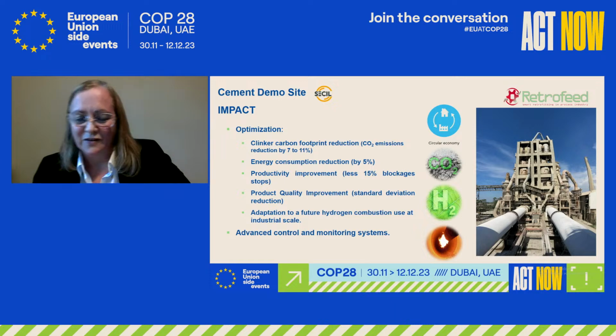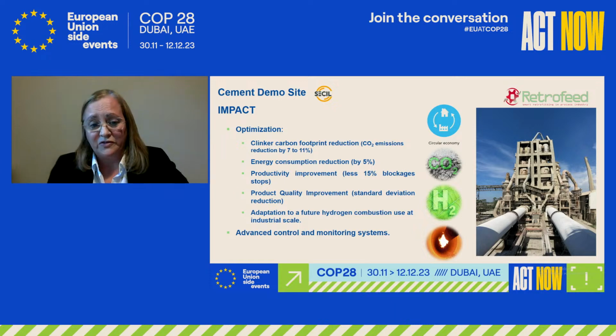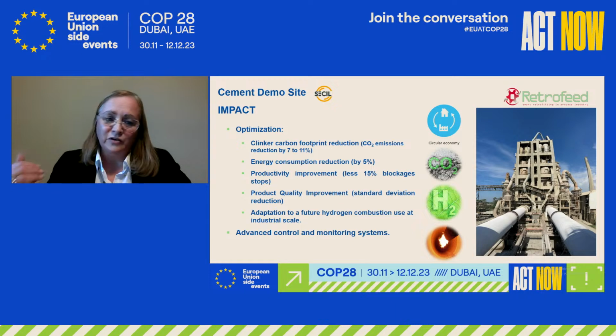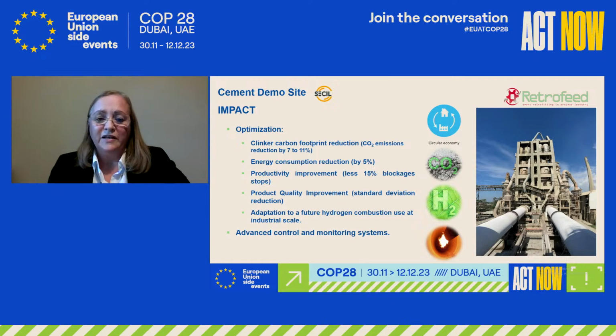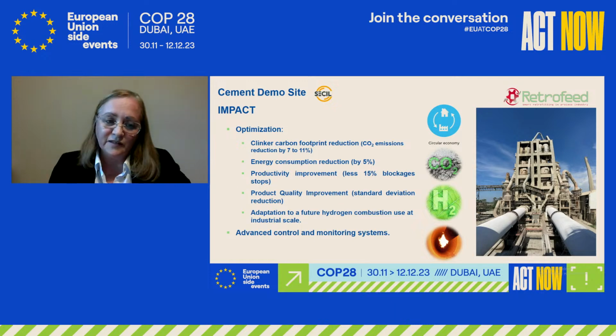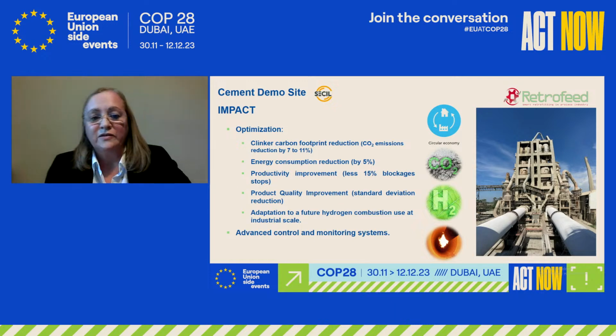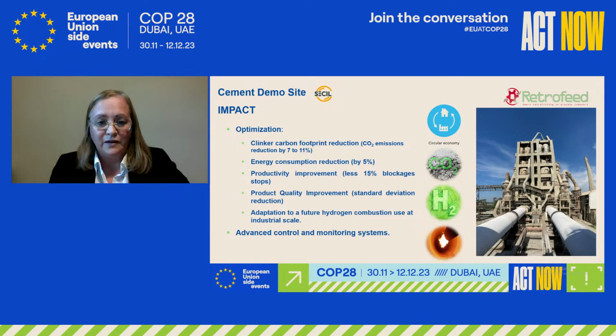So the overall impact on this demo site is basically process optimization and an advanced control and monitoring system that lead us to a clinker carbon footprint reduction from 7 to 11%, an energy consumption reduction by 5%, as said before, a productivity improvement. In fact, we get a much more stable process, so there is not so much stoppage and blockage. We can improve clinker quality because the standard deviation we will reduce, and we are ready, we can say, for a future hydrogen combustion use at industrial scale as long as we have this supply available.